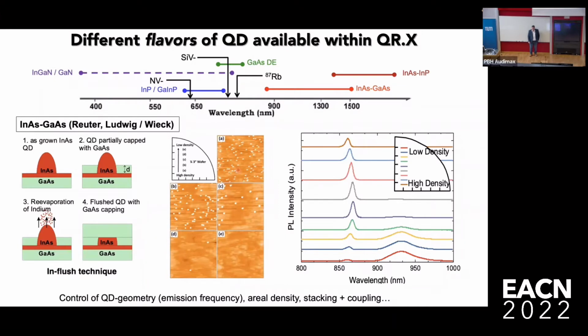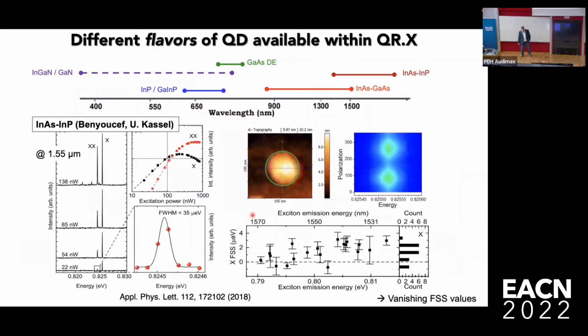And you can also control the density on the semiconductor substrate. I showed you some hyperspectral imaging where you could identify single dots. There you see a typical picture of a wafer. This is the quantum dot emission. This region here is where we take the low density, where we can isolate single dots from. So that's an example for dots emitting around 950 nanometers.